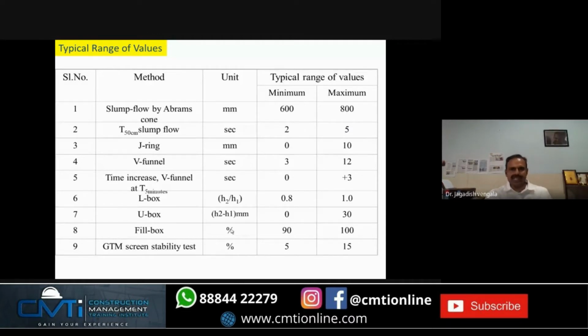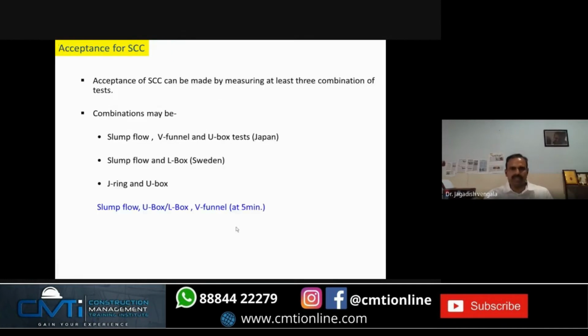When you sum up all these tests, like slump flow, 600 to 800, the limits are like this: T50, 2 to 5 seconds, J-ring, less than 10 mm, V-funnel, 3 to 12 seconds, V-funnel at T 5 minutes, plus 3 seconds, L-box, blocking ratio, 0.8 to 1, U-box, height difference, less than 30 mm, fill box, it should fill 90 to 100%, GTM screen stability test, it is between 5 to 15%.